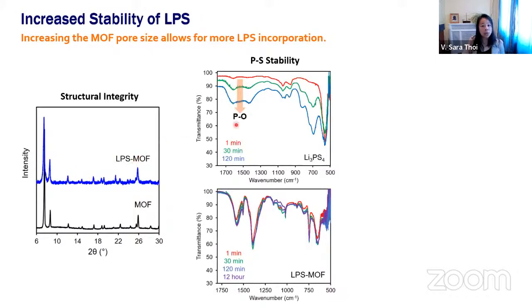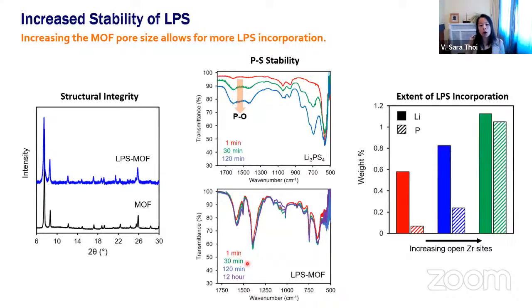We can also show that the LPS molecule within the MOF is indeed stabilized. Here you see if you take the neat material, Li3PS4, hydrolysis occurs relatively rapidly within about 2 hours. Whereas inside the metal organic framework, we really don't see the hydrolysis product of these phosphates forming even up to 12 hours. We could also play around with how many of these organic linkers we remove, which then allows us to incorporate more or less LPS in order to test our theory.